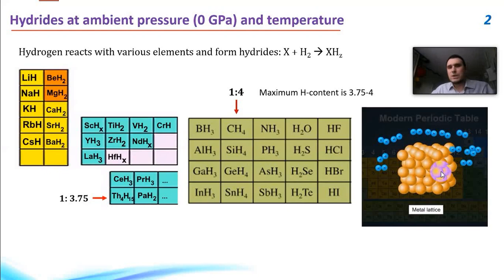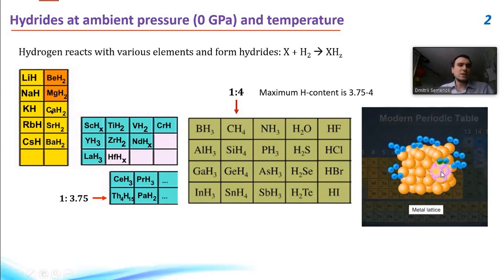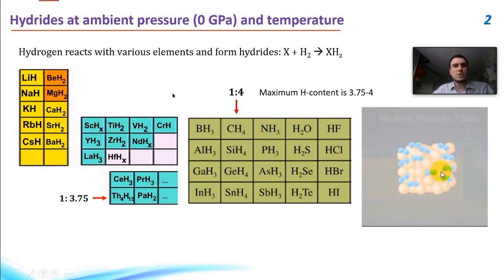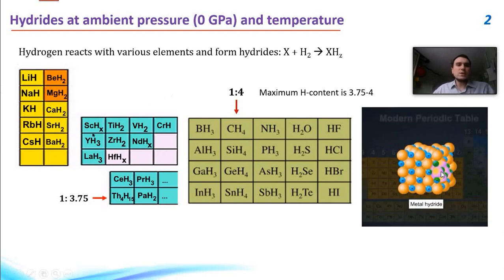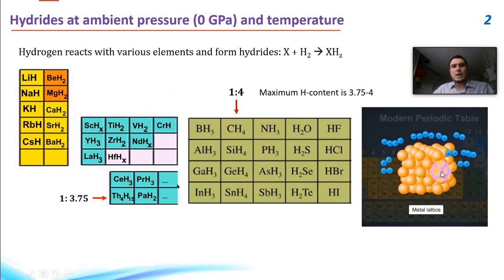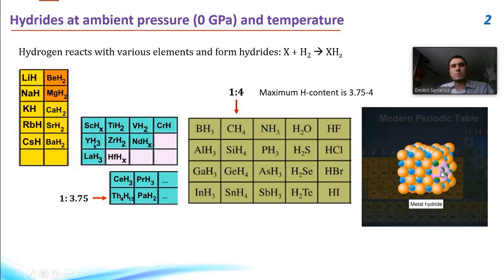Hydrogen, even at 0 GPa at normal conditions, can react with many metals and non-metals. The temperature of reaction is typically something like 500, maybe 1000 kelvins. With alkali metals and alkaline earth metals such as lithium, sodium, potassium, magnesium, calcium, hydrogen forms ionic lower hydrides. With yttrium, lanthanum, and lanthanoids, it forms trihydrides such as LaH3, CeH3, and that's almost the maximum content of hydrogen in the metallic part of the periodic system.